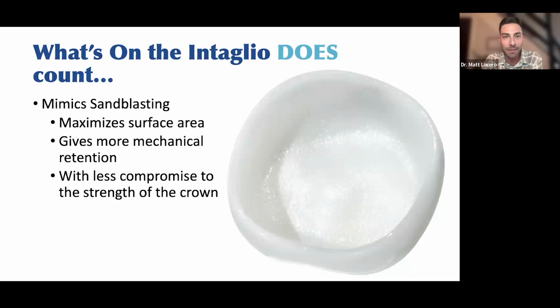So if we remember back in biomaterials class, the more surface area we have, the more retention we get on our crowns. And I'll show you the comparison to the other manufacturers here in a second. But you can see how much detail there is in that intaglio, and you're not going to have a lot of changes on the thickness of your crown. It's going to be pretty uniform throughout. And that leads to less compromise and less fracture of the crown as well.